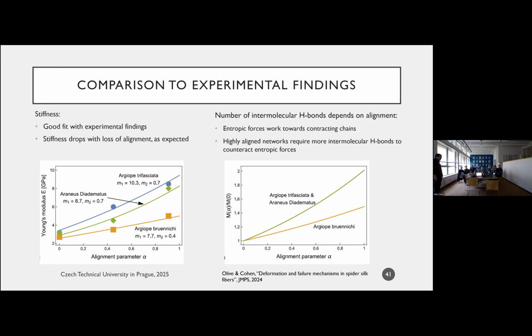In addition, what I'm plotting here is the number of intermolecular bonds that formed between chains as a function of the alignment parameter. And what I'm arguing is that the more I pre-stretch the material and let it dehydrate under tension, the more bonds are going to form, because I need more agents or bonds to counteract the entropic effects. So if I have a chain and I start stretching it, if I want to keep it stretched, I'm going to need a lot of intermolecular bonds to counteract the entropic forces that want to contract it. So the more I stretch the chain, the more intermolecular bonds I need, or the more constraints I need to maintain this orientation or this conformation.